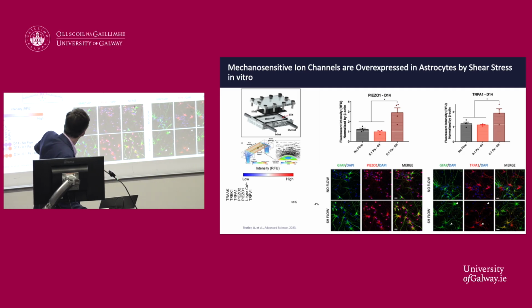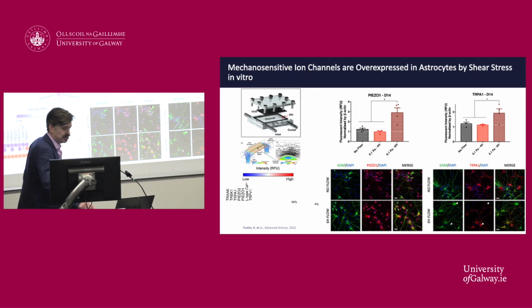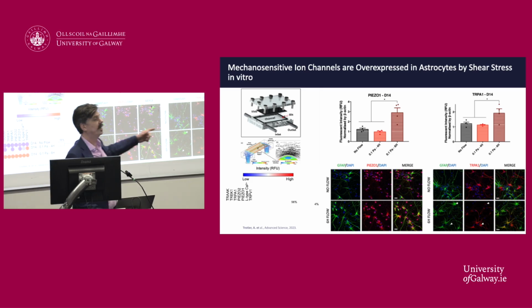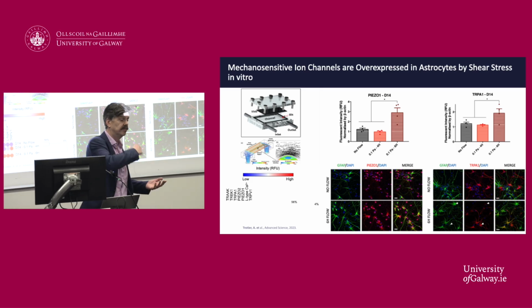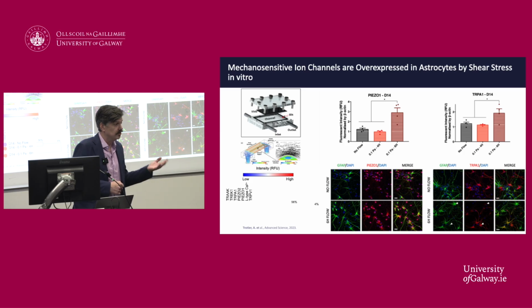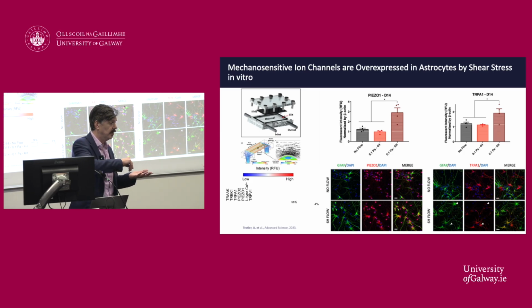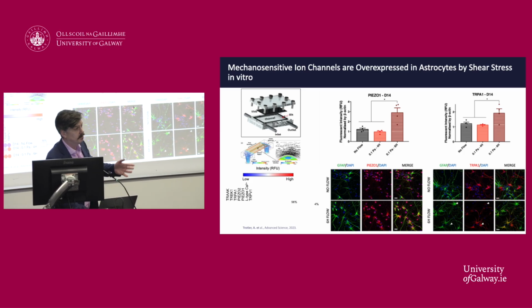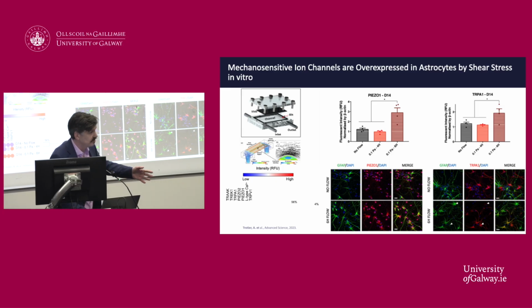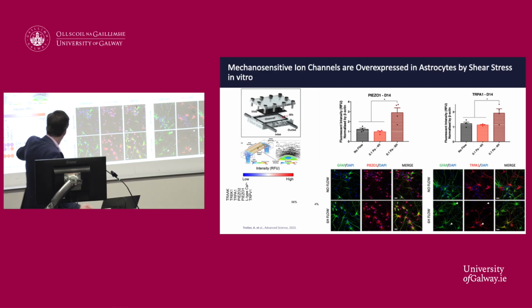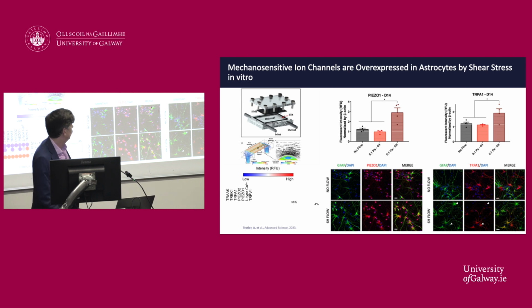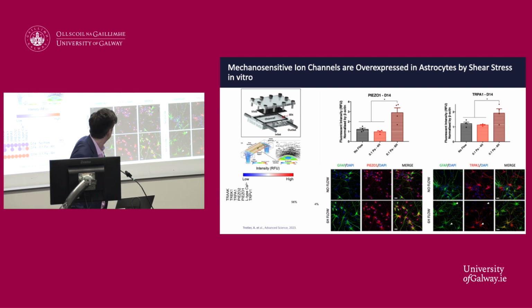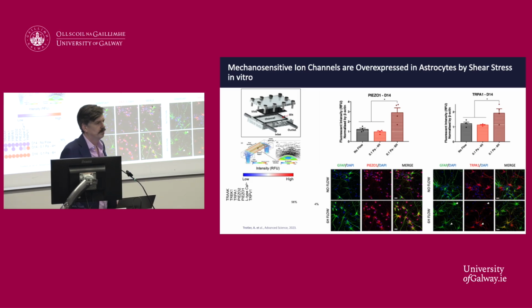So we assayed for these, and we found that if we subjected cells to shear, we used a very simplified system where we can use mechanical shear via fluid flow. We can culture neural populations onto a bioreactor system, flow media over them, and the cells become subjected to shear stress. This shear stress causes upregulation of the expression of multiple ion channels, and we found 2 were significantly upregulated, even at really low shear stresses. So we found these were responsible for some of the inflammation that was happening around the electrode.